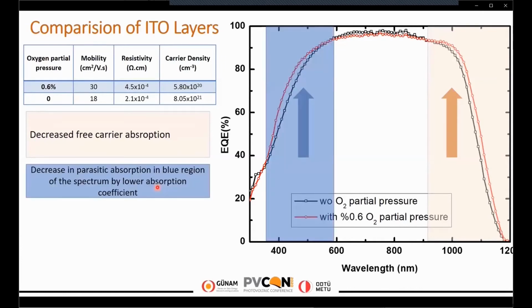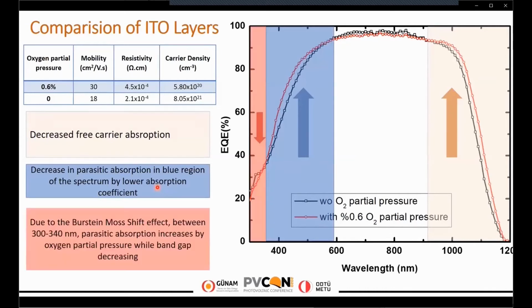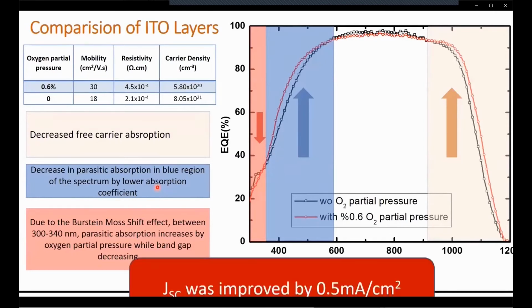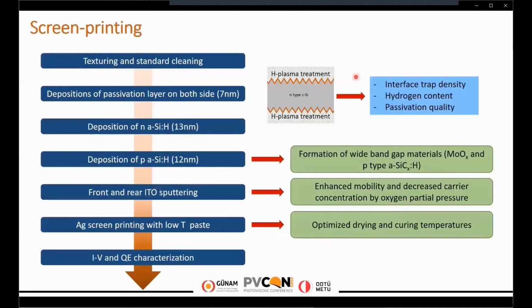In the blue region of the spectrum, enhancement is achieved by a decrease in the parasitic absorption, but below 340 nanometer, due to the Burstein-Moss shift effect, parasitic absorption increases with respect to the decrease in the band gap value of the ITO. Overall, we improved current density by 0.5 mA per centimeter square, only by changing the ITO layer. Let's continue with the screen printing part.